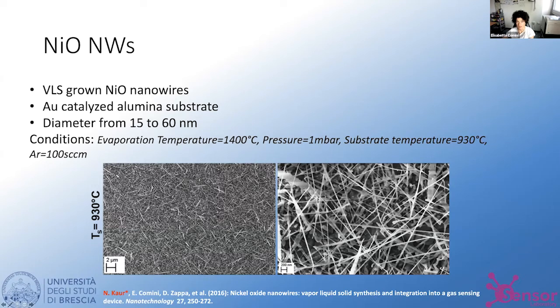Also in the case of nickel oxide, the best catalyst for the growth has been gold. And it was difficult to achieve nanowires since the evaporation temperature of nickel oxide is really close to our limit of experimental setup, so 1,400 degrees C. And also the substrate temperature for the condensation is very high, as you can see here, more than 900 degrees C. But at the end we were able to achieve this nanowire morphology.